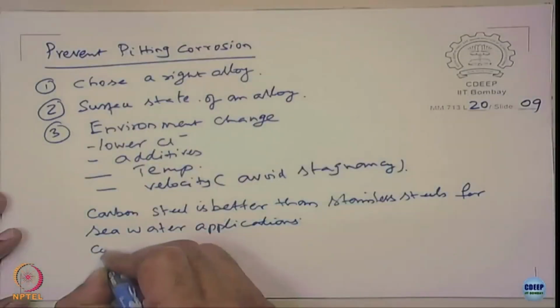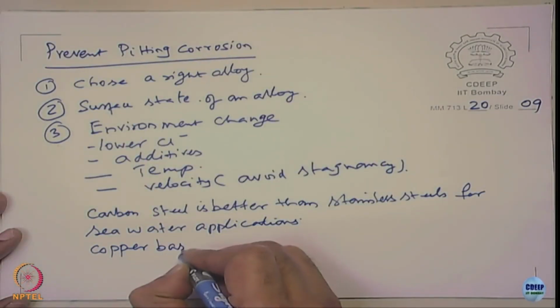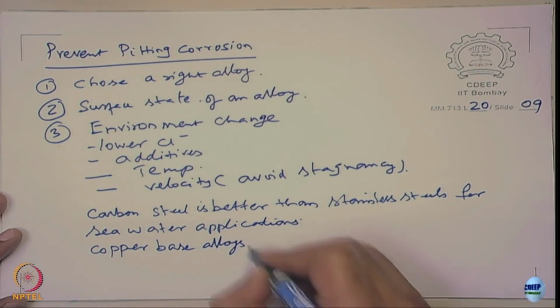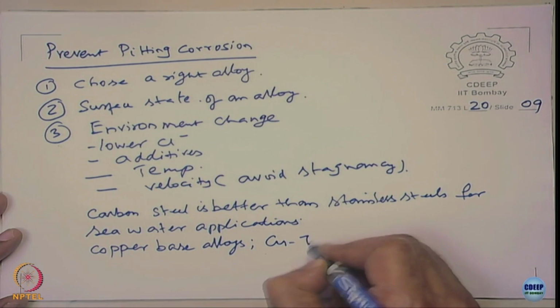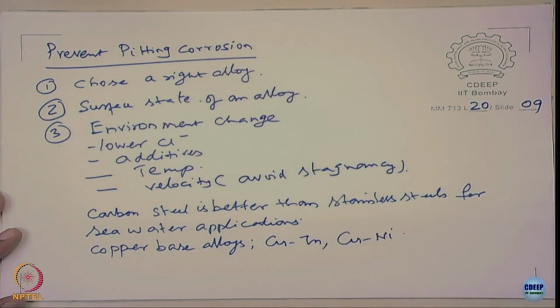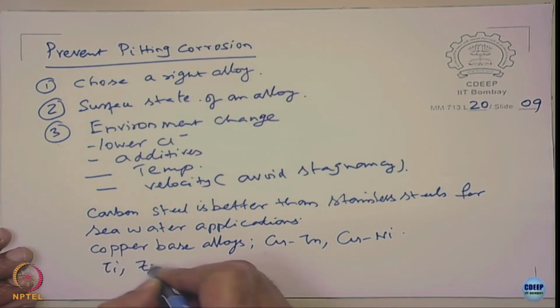But if you have a problem with uniform corrosion, then you go for copper based alloys. What are the alloys that you can think of? You can think of brass, you can think of copper nickel alloys, right. They are all used in seawater applications. They have reasonably good uniform corrosion resistance compared to carbon steels, and they do not pit, and so they are in fact widely used for seawater application. The other way of looking at it is you have very strong passivating metals and alloys, that is, we saw the PRE number. Similarly, you can look at titanium, zirconium, these all can be used.